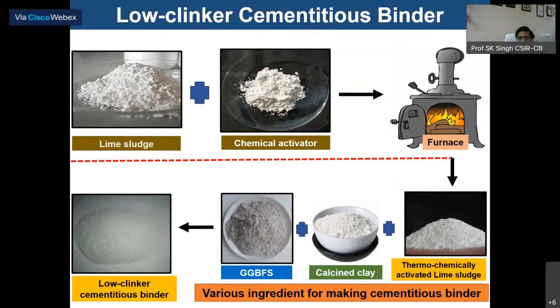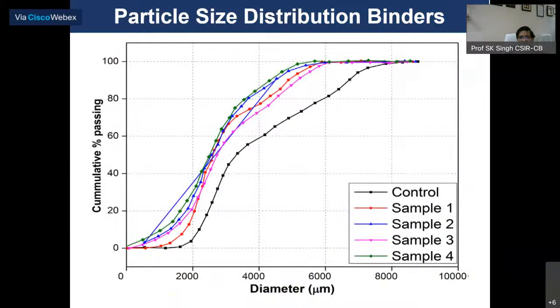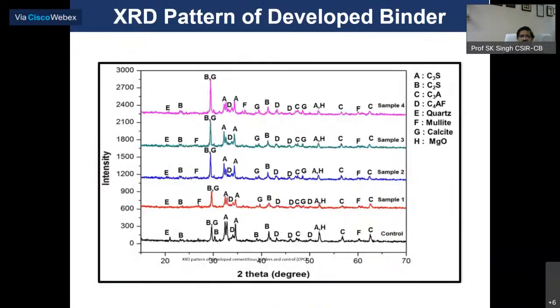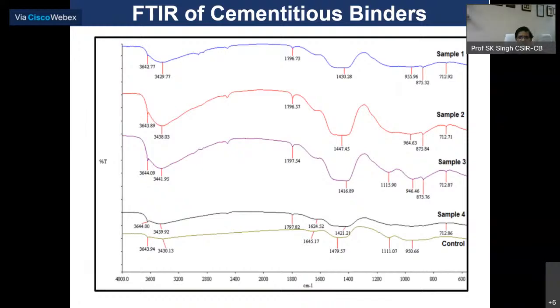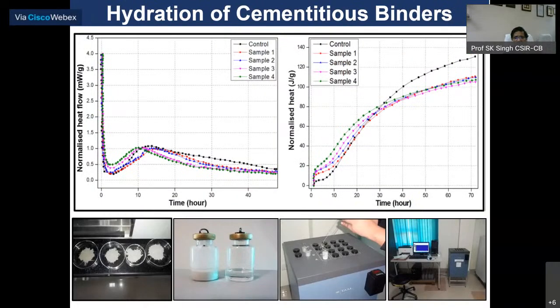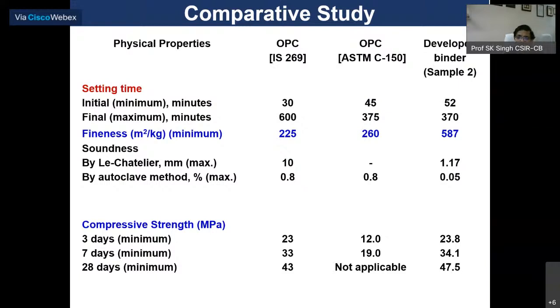Also, the different activities I told you about that we have carried out, and this is the different composite cement we have made. We found that sample 2, which has about 25% lime sludge and some calcined clay, with 50% ordinary Portland clinker used, gives a denser structure, mainly. I'm not going into much detail, because it is given in my paper. Here we have compared the results with ordinary Portland cement and our developed binder as sample 2, and comparatively similar results were found.